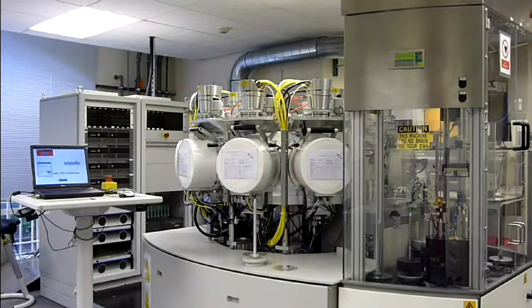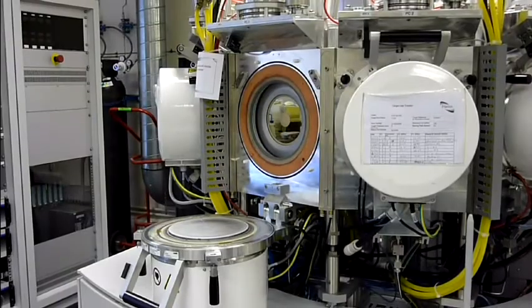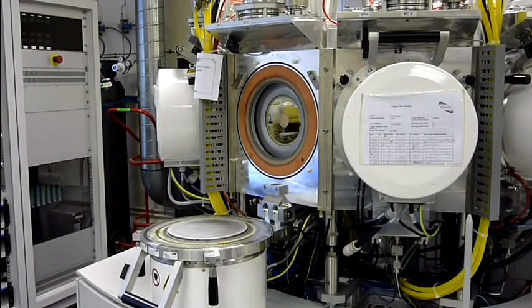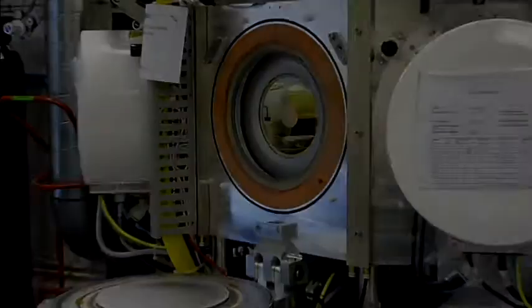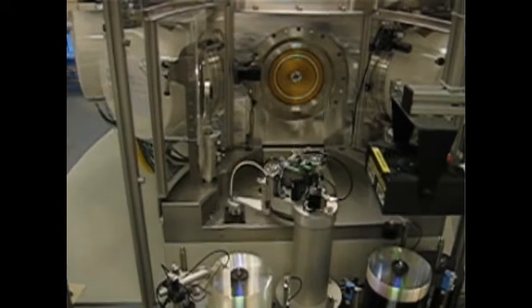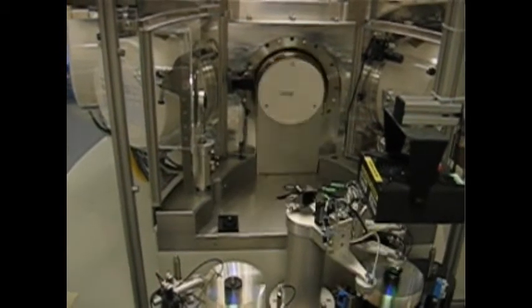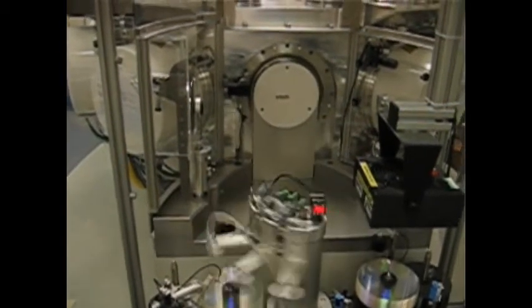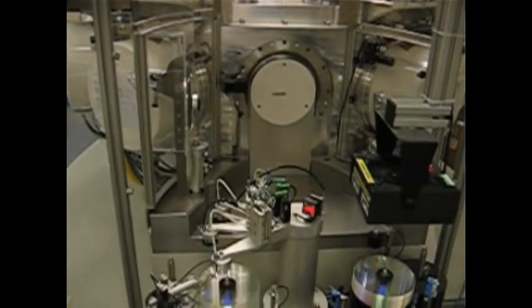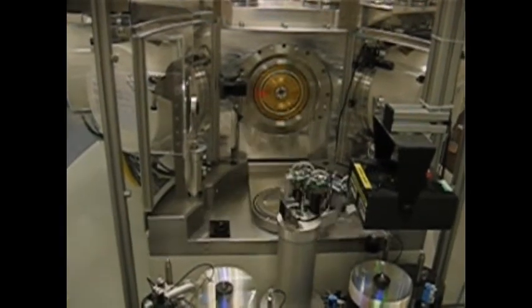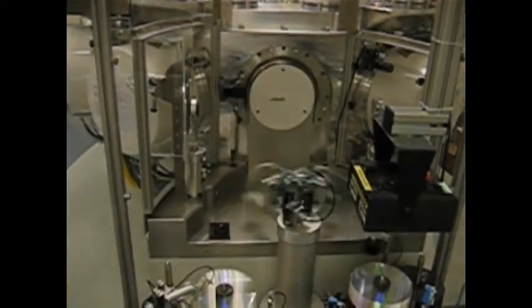The 9-chamber vacuum sputter coater at Plarion operates in both DC and RF modes and can deposit up to 30 layers without breaking vacuum. Layers may be as thin as a few nanometers, in a wide range of materials including metals, dielectrics and chalcogenides. In reactive sputtering, a gas is introduced into the vacuum chamber, leading to the deposition of, for example, oxides or nitrides of the target material.